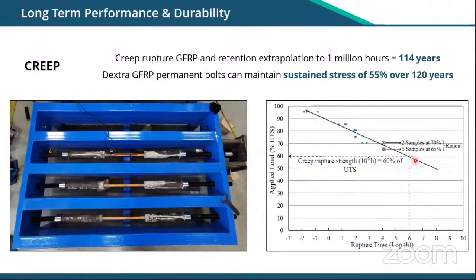It's interesting to see that there's a regression, and it's behaving logarithmically. What we concluded on our material is, if the sustained load is maintained to a maximum level of 55%, we can guarantee the GFRP material will be able to take that load over 120 years. That's extremely important, because as a designer, once you start designing a structure, you should be able to limit the sustained load to this value.